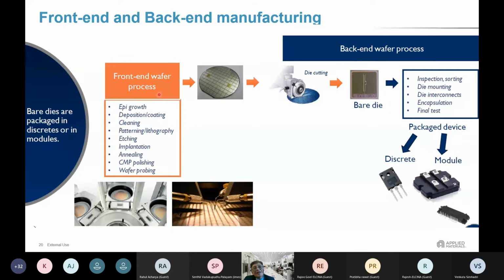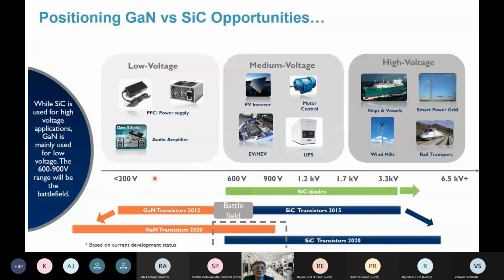Conventionally, the front end where the wafer is processed, and the back end of the factory where the dies which are made in the front end are getting inspected, sorted, die mounted, encapsulated, final test, and the final product comes out, which is what you see. So the heart of it is, of course, the die, and you see the processes here: the epitaxial growth, deposition, coating, cleaning, litho, etch, implant, anneal, polishing, wafer probing, and some of these processes are done several times. So in a typical device creation, for example, in CMOS, it can run to over 1,000 steps. So it's a pretty rigorous, process intense thing.